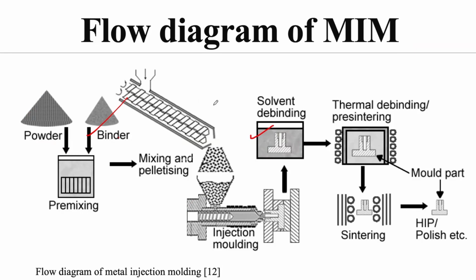And then you go to the next step, which is the thermal debinding process, pre-sintering, followed by the sintering process. In these two steps, you are going to put this debound part into a tube type sintering furnace, where inert gas, something like argon, is being supplied. The temperatures over here will be something around 1700 degrees or 1600 degrees, depending on the material that you are using. At those temperatures, the metal powders will start to fuse together, and whatever polymer you added will degrade and evaporate.